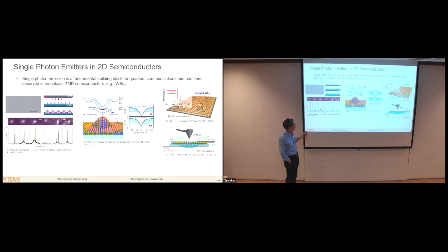And so there are a variety of ways to create these types of structures. One shown here is basically that you take a monolayer of these materials and you just sort of drape it over an array of nanopillars, and then you have tensile strain near the apex of the pillar. You can also do similar things by transferring these materials onto an array of nanoparticles, or by using an AFM tip to sort of push the material into a soft substrate as shown here.